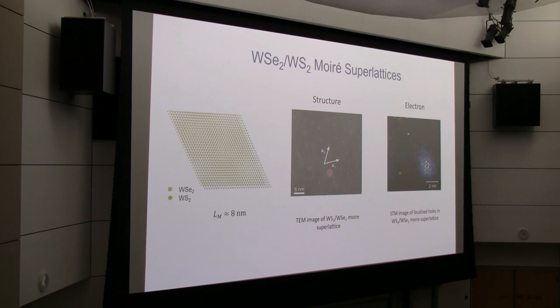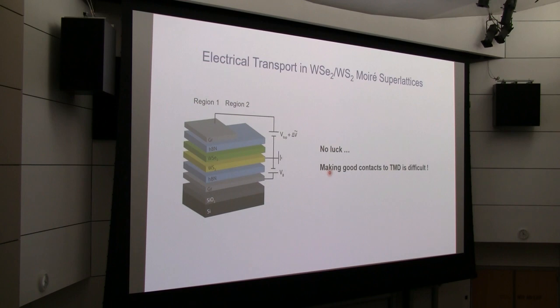These two materials have a lattice constant mismatch of about 4%. So when you stack them together, even when they are perfectly aligned, they have a Moire period of about 8 nanometer. And structurally, we can indeed see the Moire period using a high resolution TEM, where you can see this periodic atomic structure. And if we do STM on this sample, we find this atomic structure is really providing an effective potential for electrons. So the electron wave functions are not homogeneous anymore. They are rather localized at specific points. So with this Moire period and the large period electrical potential, we should expect strong correlations.